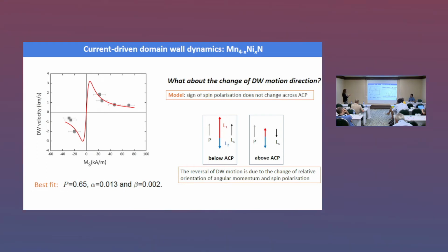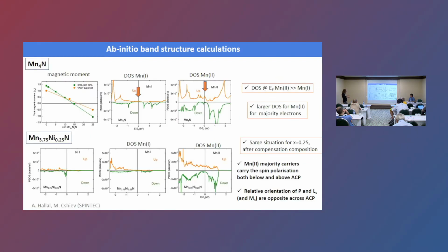In order to explain this, we have to prove that the spin polarization does not change direction across the angular compensation, and for this we asked our colleagues from SpinTech to carry out band structure calculations. They considered two systems, manganese nitride, undoped and doped sample, on the other side of the compensation. These are the density of states at the Fermi level for manganese 1 and manganese 2. What they found out is that